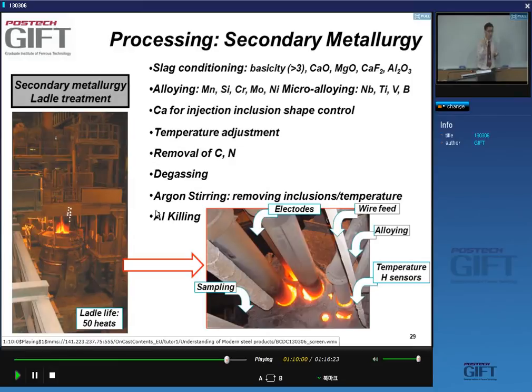Yes, oxygen and carbon. Remember, I want carbon in my steel. In certain cases, I will add carbon to my steel. Yes, the solubility will decrease, and the CO will start forming bubbles. And if you don't do the aluminum addition, the solidifying metal will suddenly start to foam and bubble. And you will not be able to cast anything, yes?